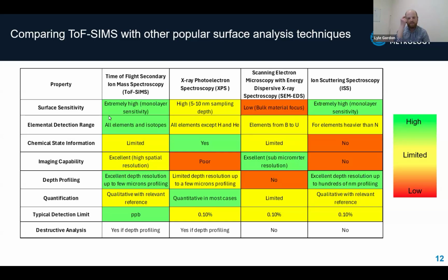Let's talk a little bit about when you might choose ToF-SIMS versus some of the other surface science techniques that we offer at Covalent. If you don't need the high spatial resolution, then XPS can be a really good choice. It gives you simpler quantification, where most of the time you don't need standards to get accurate quantification, and you also get chemical information like oxidation state, which can be really valuable for understanding different impurities.